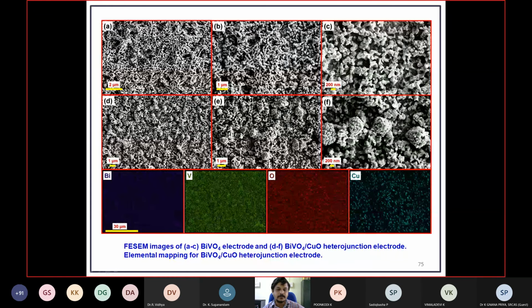In the first, A to C, the FESEM images show the formation of the bismuth vanadate electrode. Then D to F, the copper oxide is covered over the surface of this heterojunction. Later we have done elemental mapping analysis. It clearly reveals the presence of bismuth, vanadium, oxygen, and copper on the surface of the heterojunction material.